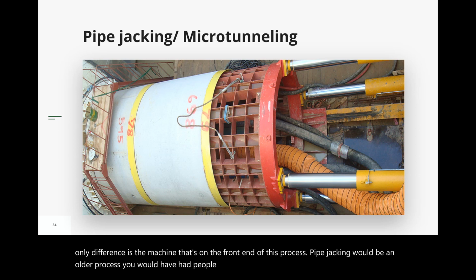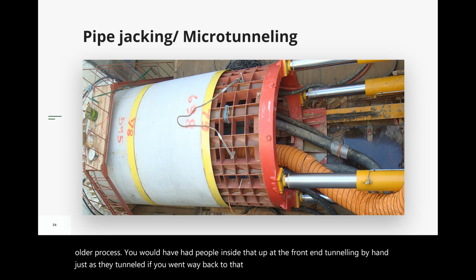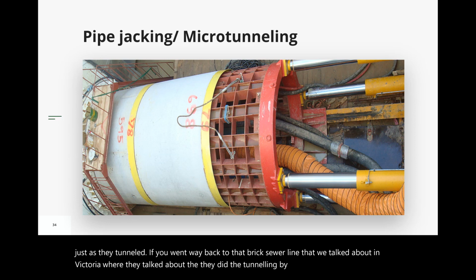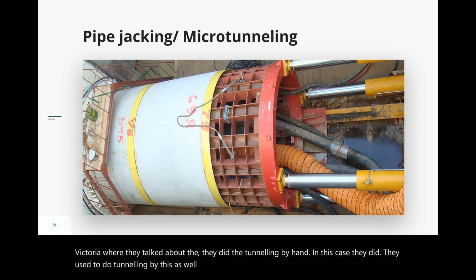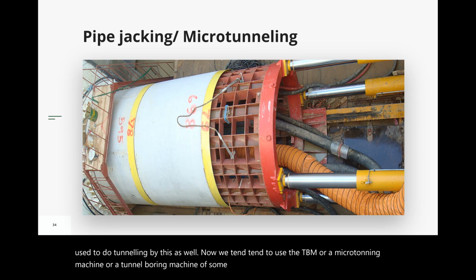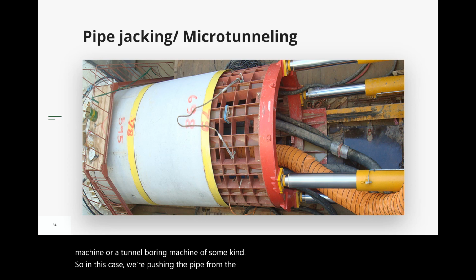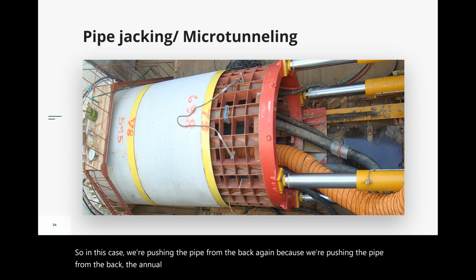So in this case, we're pushing the pipe from the back. Again, because we're pushing the pipe from the back, the annulus is only 25 to 50 millimeters on the outside of those pipes. You do tend to limit out after 60, 80, 100 meters. So micro tunneling and or pipe jacking are limited to those kinds of lengths before they start to slow down. Obviously, you can make the hole at the annulus a little bit bigger and continue on a bit more, and it depends on the soil types, it depends on lots of different things.